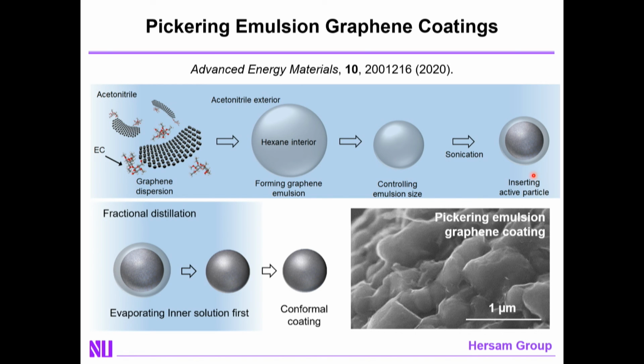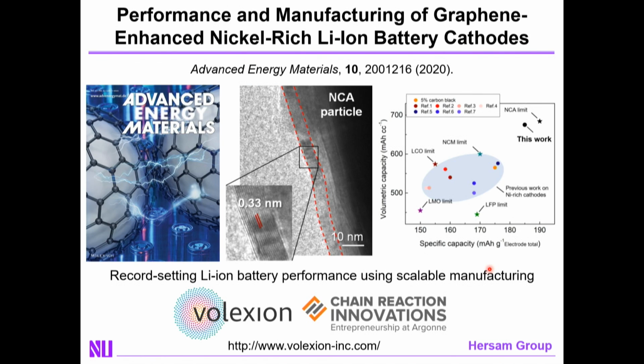The final trick is to exploit fractional distillation, namely the fact that hexane has a lower boiling point than acetonitrile. And as a result, upon heating, the inner solvent evaporates first, causing the particle size to decrease and the graphene to collapse around the surface of your particle, giving you a beautiful coating at an order of magnitude less graphene than you had in the previous random mixing approach.